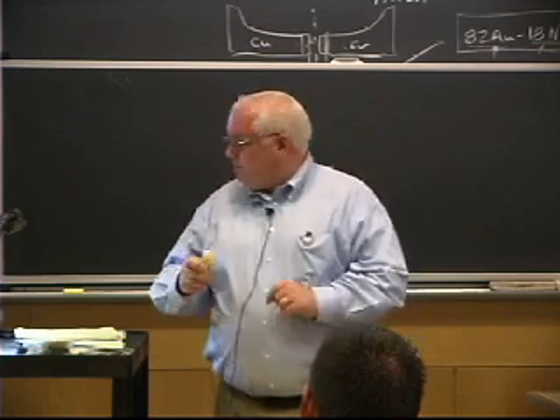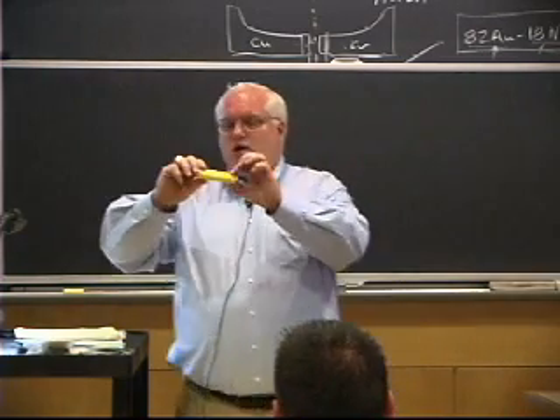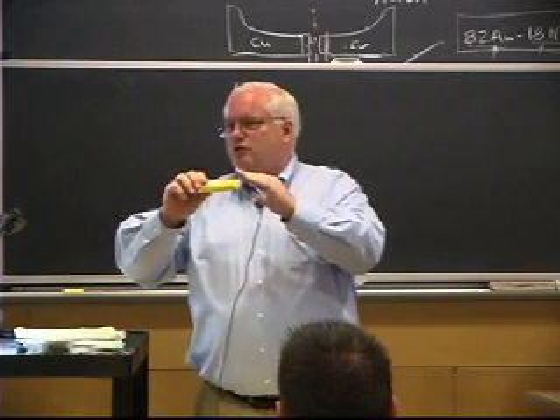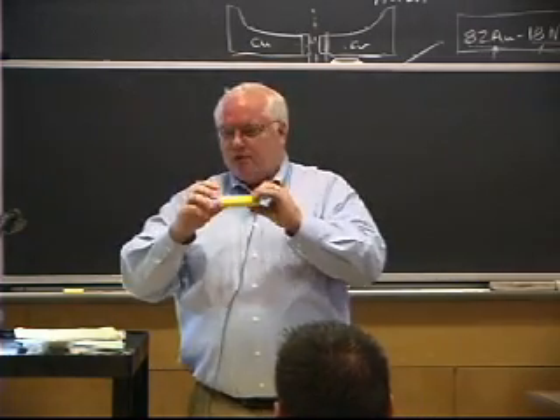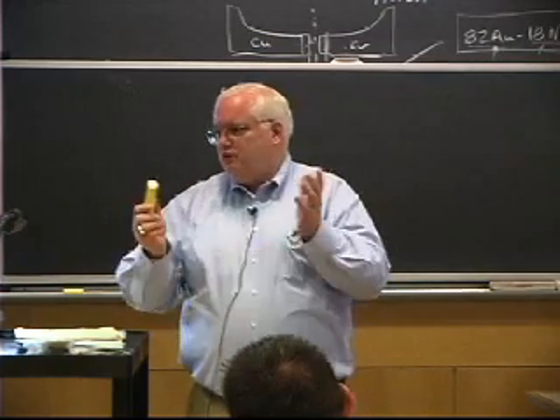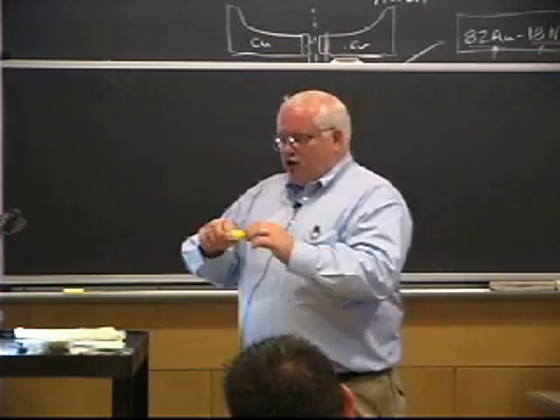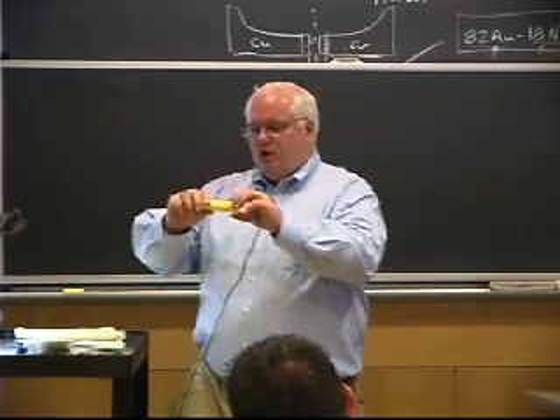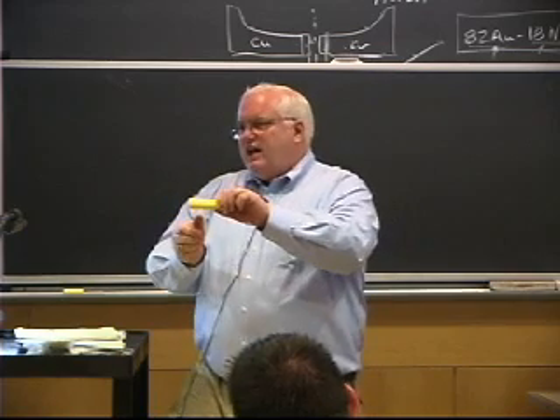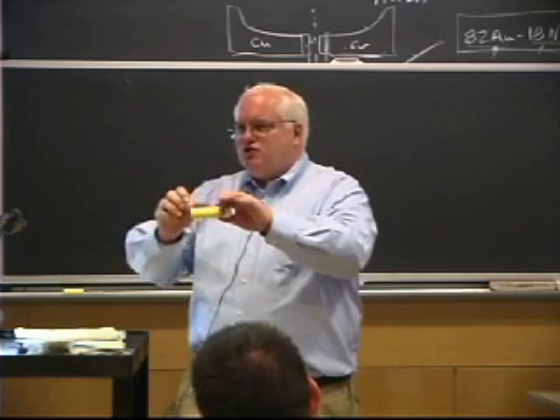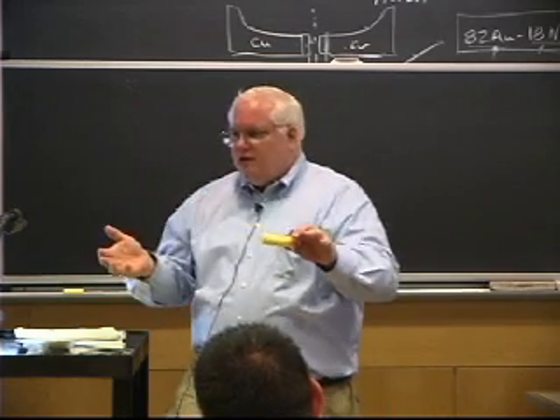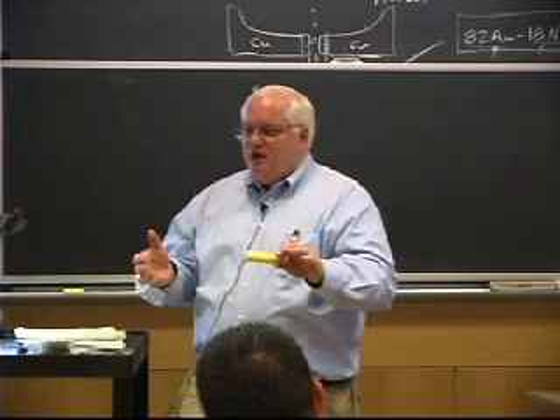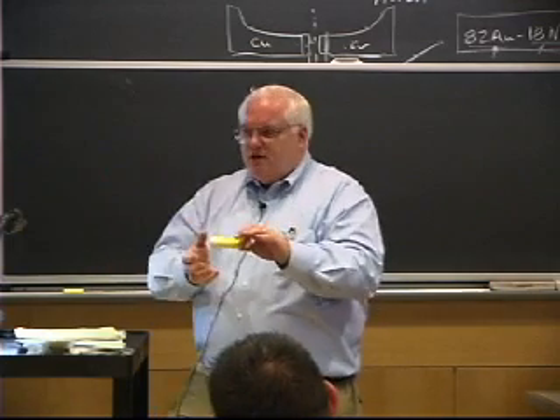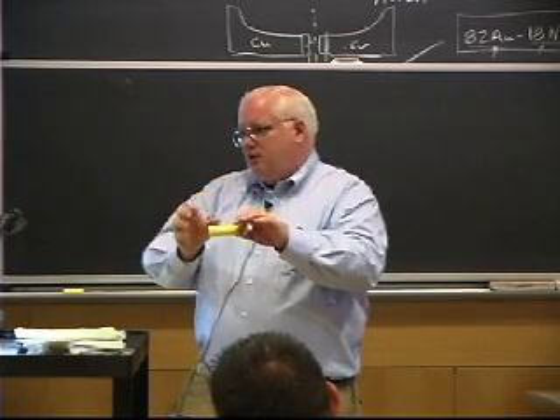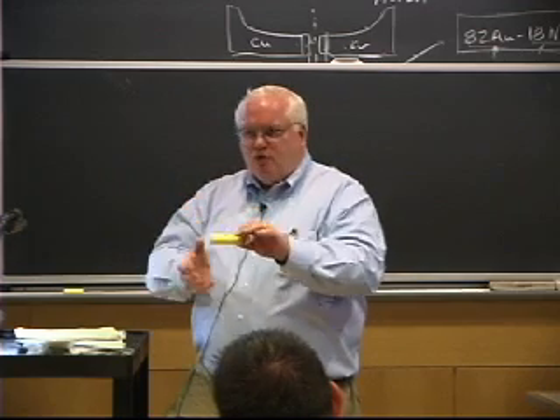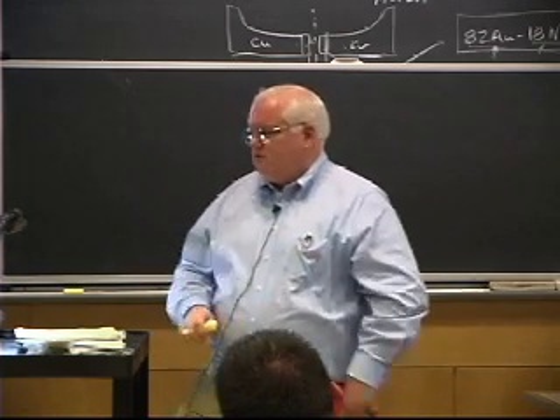pretty well. It turns out this particular one, if you took the part and bent it, you could get like a 2-degree bend angle on that molybdenum and copper before the thing would just snap. No real ductility at all. And they showed me a piece with this new braze alloy that they had bent like 90 degrees, and the copper had just stretched. No brittle intermetallic, wonderful joint. The molybdenum is much harder, so it hadn't deformed, but the copper, being a nice soft ductile metal, had just deformed tremendously. So this thing would take tremendous stuff.